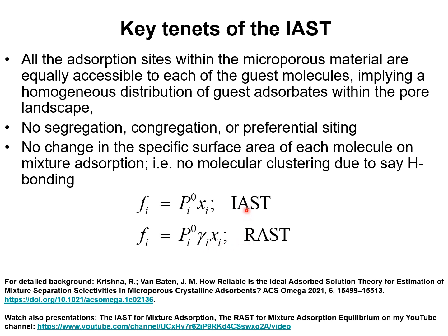And when the activity coefficients are accounted for, we have the real adsorbed solution theory. The modeling of the activity coefficients could be done by invoking the Wilson model for the excess Gibbs free energy, the NRTL model, or the Margules model.